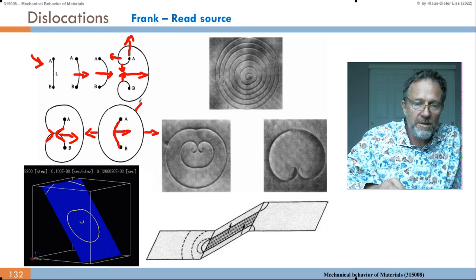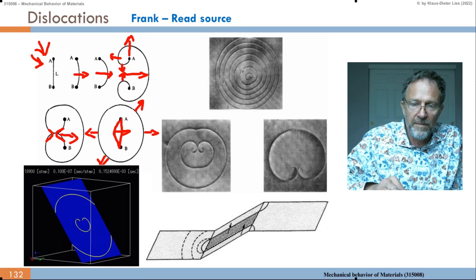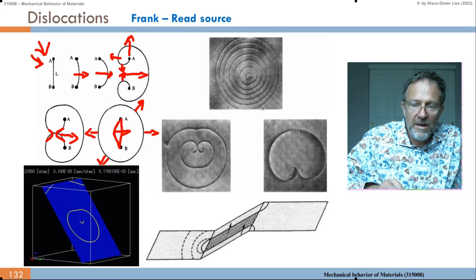We have a dislocation loop now, the classical dislocation loop, which expands in all directions. And then when this line becomes straight, we start over with the top of the figure, A to B, bend out again, curl around, recombine where they touch, and have another loop. And that gives us, upon a lot of shear, one loop, the next loop, and a lot of concentric dislocation loops.